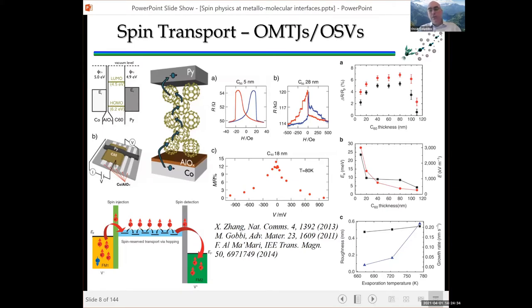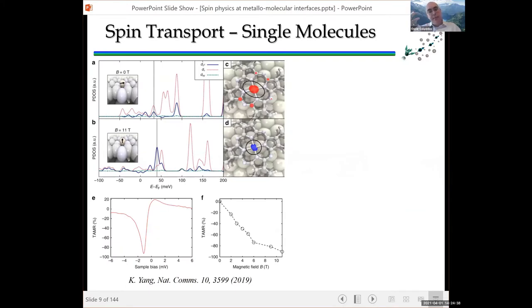Then, of course, once you have measurements in thin films, people wanted to do the same thing in single molecules. So there was this recent report from Yang et al. where they did measurements using a scanning tunneling microscope, and what they saw is that the magnetoresistance is very heavily dependent again on the sample bias, to the point that you can have anything from a negative magnetoresistance of almost 100% to a positive magnetoresistance of 20%, depending on the voltage you apply. This is partly because the conformation of the molecule and how it links and hybridizes with the metal substrate is very dependent on the applied electric field and also on the magnetic field. So you even have a change in the slope of the magnetoresistance depending on this actual applied magnetic field.